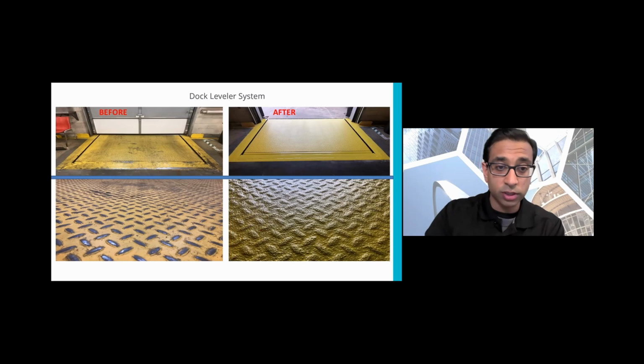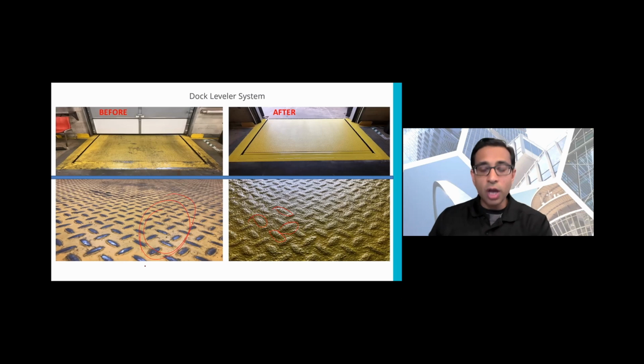Well, if you look closely, what is done is that an epoxy system is actually put in. The surface is prepped, an epoxy system is put in, and then an aggregate is put on top of it. So if you look closely, you could see here's all the bumps, but there's a lot of bumps in the bumps. That's a lot more surface area compared to what you're seeing on this side, right? So now you increase the amount of friction.